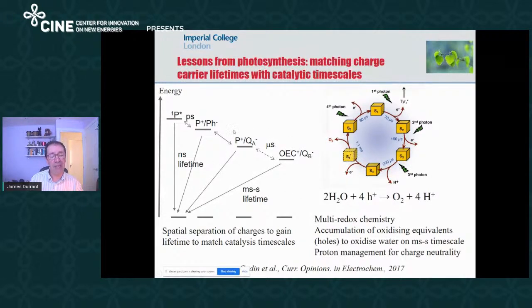Plants do this by separating the charges, as I described, and they separate the charges to gain lifetime, because if the charges are separated apart, then they'll take a longer time to recombine. But of course, that separation of charge costs energy. The energy of the separated states driving the chemistry in plants is around half the energy of an initially generated excited state. So the plants lose around half the energy from the sun in driving the reactions, which enable the carrier lifetimes to be long enough to drive the catalysis. And that's an interesting challenge, because it suggests that you need to gain lifetime to drive catalysis, but that costs energy. And that reduces efficiency.